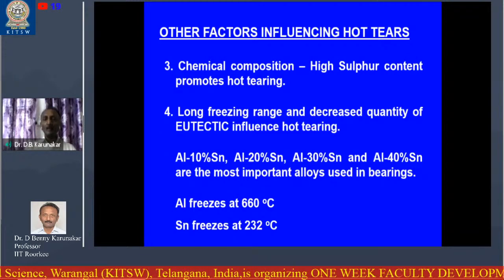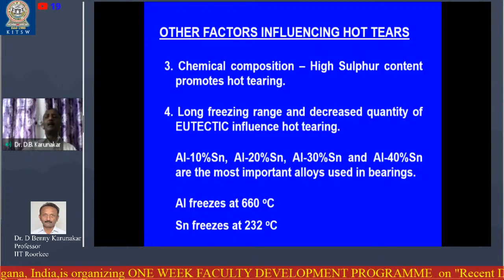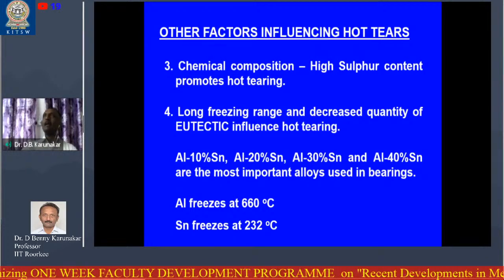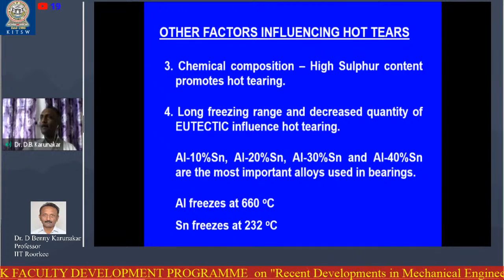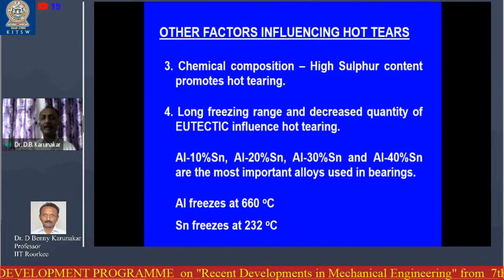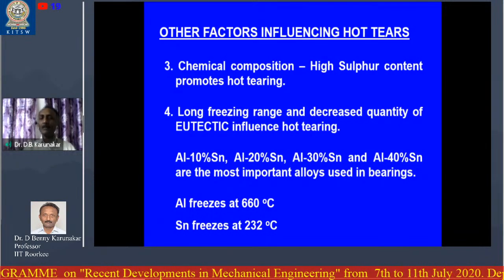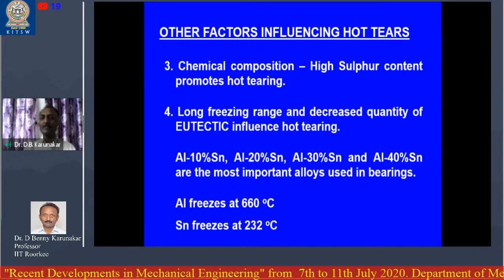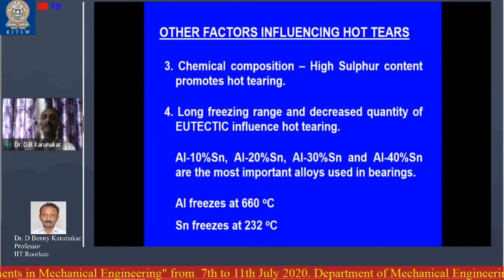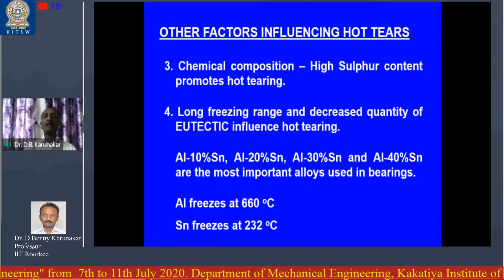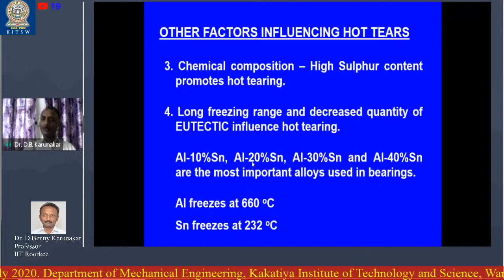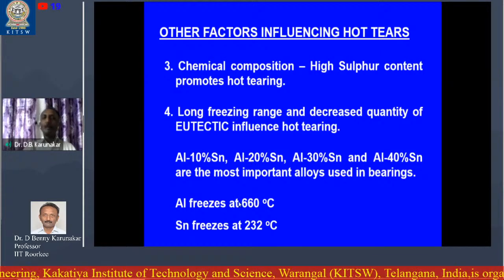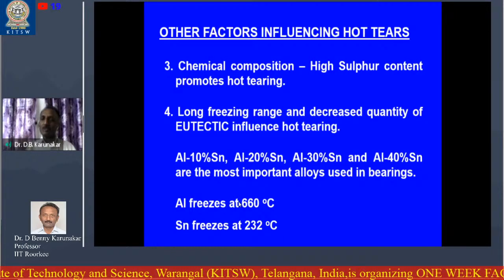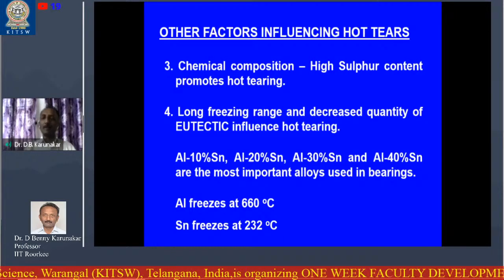Aluminum still undergoes contraction. It wants some metal. There is a gap, there is a discontinuity. Come and help me, but there is no tin available. And if this situation persists, there is more and more contraction, finally leading to hot tearing. So this is the major factor responsible for hot tearing. So long freezing range can strongly influence hot tearing in casting.